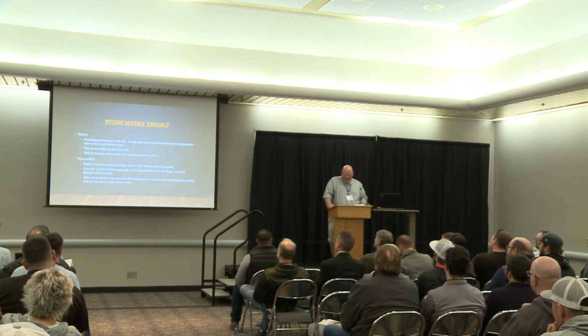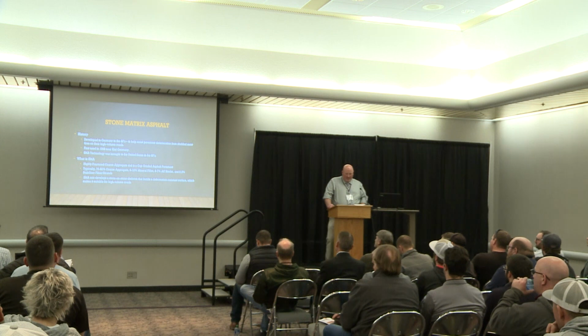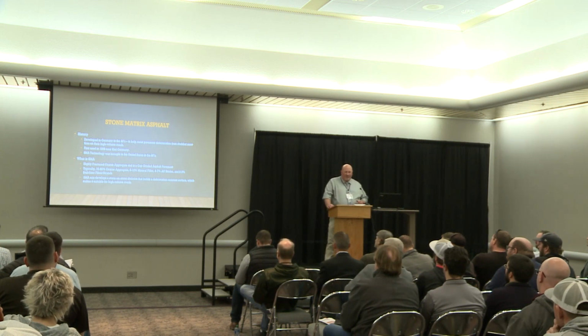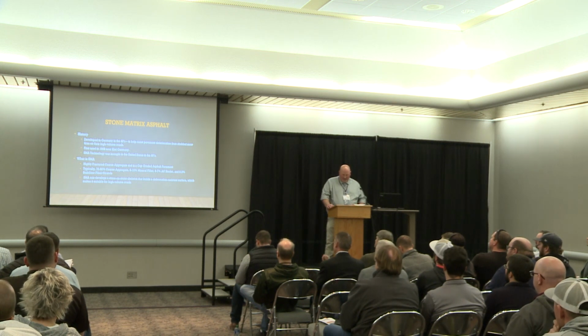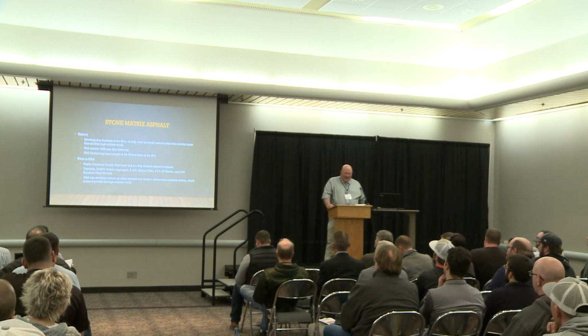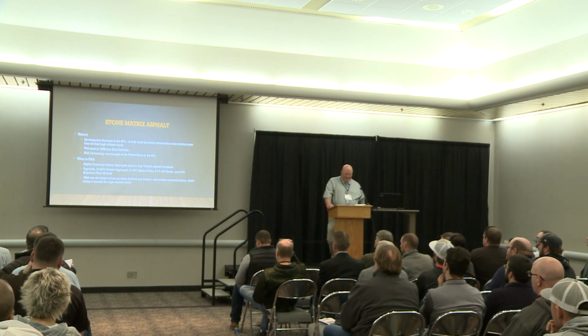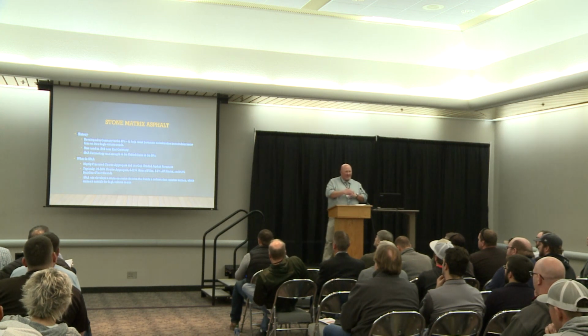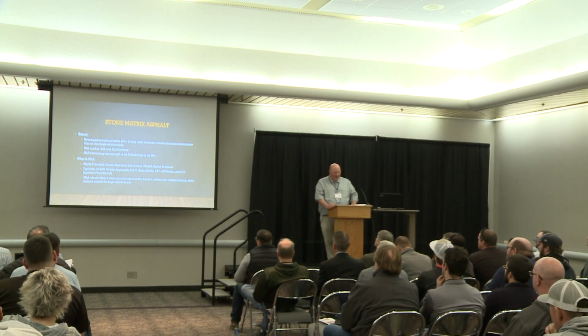So what is an SMA? It's a highly fractured coarse aggregate gap graded asphalt mix. It's typically 70 to 80% coarse aggregate, 8 to 12% of a mineral filler, which is typically either a Portland cement or a fly ash, 6 to 7% AC binder, and then 0.3% of a stabilizer or fiber or a strand. And then what's unique about the SMAs is it develops a stone-on-stone skeleton in the mix that helps it carry the loads.